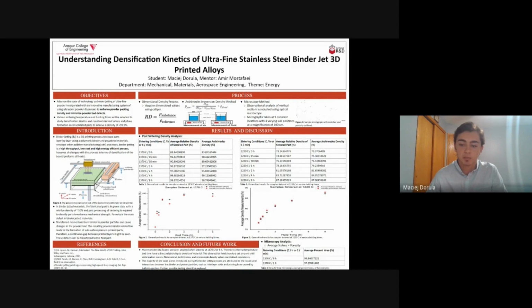Porosity is the main defect in binder-jetted materials. The majority of the large pores introduced during the binder-jetting process are attributed to the liquid-solid interactions between the binder and powder particles, such as the interlayer voids and printing lines caused by ballistic ejection. With this in mind, using the optical microscope, a total of 36 images were taken at set positions to determine the porosity of each sample.